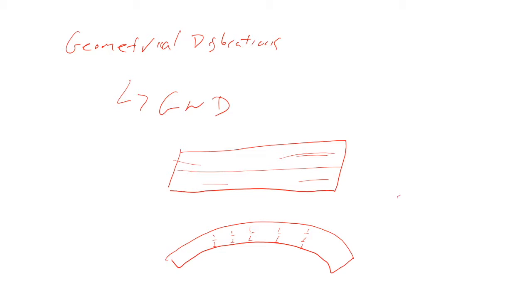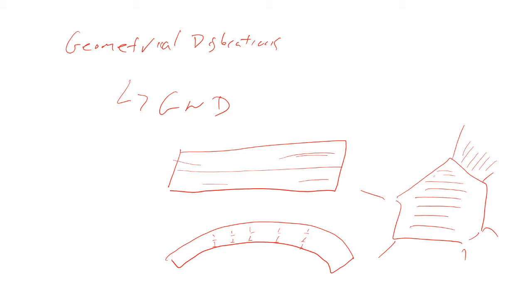You can imagine if I've got a grain here, these grains all have neighbors, right? If this is an easy grain to deform, and I'm at room temperature, or at a low homologous temperature, this grain deforms plastically. I'm not opening holes in my material, so I need to maintain a compatibility of my deformation. That means I'm going to have deformation that happens in this grain, either due to the activation of pileups or for other reasons. And if this is also a hard grain down here, by hard grain, I mean one that's difficult to activate, we'll talk about that in more detail in the next lecture, I'm going to have a gradient across this grain.